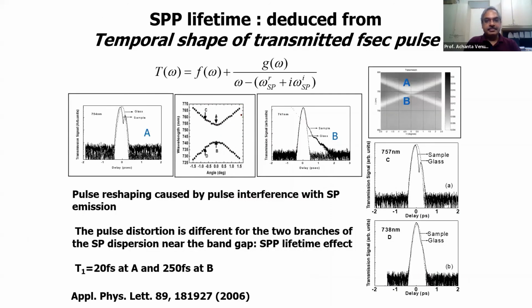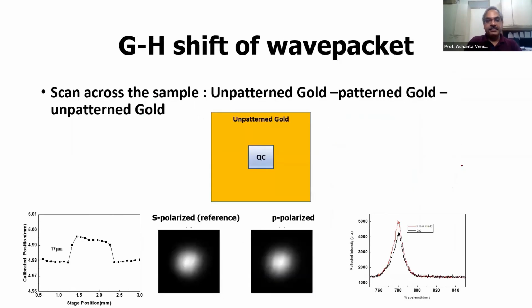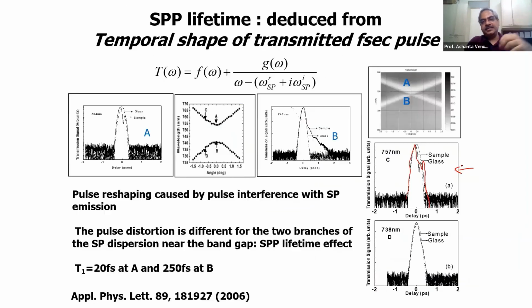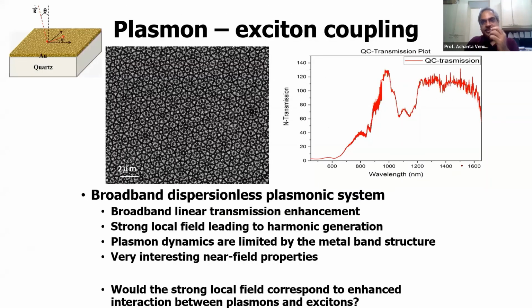This is interesting because if you have a periodic grating, when you launch light, you see that the short pulse is getting distorted. So there's a chirp in the pulse. But here, if you have a broadband structure, the chirp is not there. So the entire pulse can be reflected from these surfaces without any distortion.